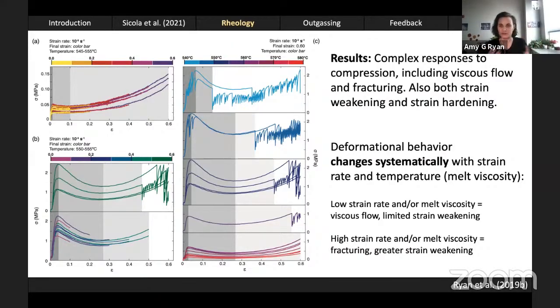You might not be able to immediately see this, but I'd like to assure you that the deformational behavior changes systematically in this material as a function of strain rate and temperature, which is to say melt viscosity. To summarize, at low strain rates and or low melt viscosities, I tended to observe viscous flow with limited strain weakening. So a curve like these ones would be representative, or these red ones at the bottom. At high strain rates and or high melt viscosities, I tended to observe fracturing and a greater magnitude of strain weakening. So representative curves would be some of these ones here or these ones over here.